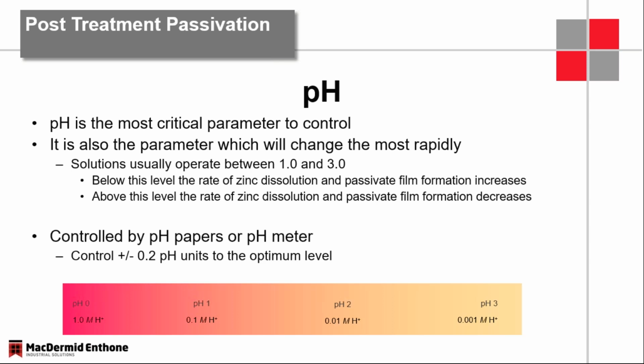So controlling the pH, pH papers will work as long as you can still see the color change. The trivalent Passivates are usually darker in color, so pH meters are important. Automatic control on your plating or on your Passivate solution is highly recommended. The pH probes need to be cleaned on a regular basis. You really, really need to monitor that in the range of about 0.2. So if your standard operating pH is 2.3, your window would be 2.1 to 2.5. And you'll notice a difference in performance and appearance at 2.1 as well as 2.5.